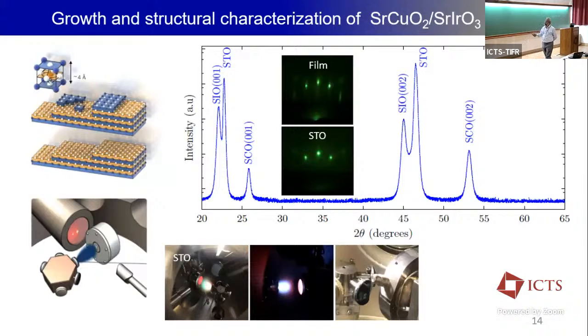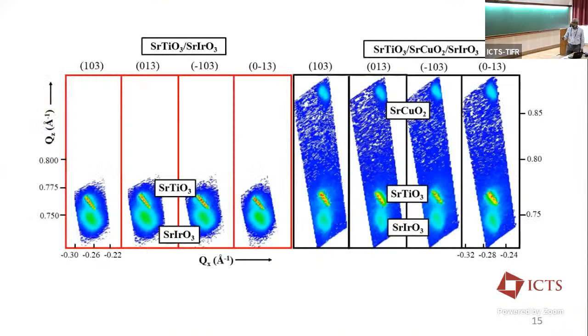We grow these bilayers by pulsed laser deposition, RHEED assisted pulsed laser deposition. I'll not get into this more. So here SrIrO3 is grown on SrTiO3, and here SrIrO3 is grown on a layer which is an antiferromagnet. Here we are growing a perovskite on perovskite, but there we are growing a perovskite on SrCuO2, which is known as the infinite layer.